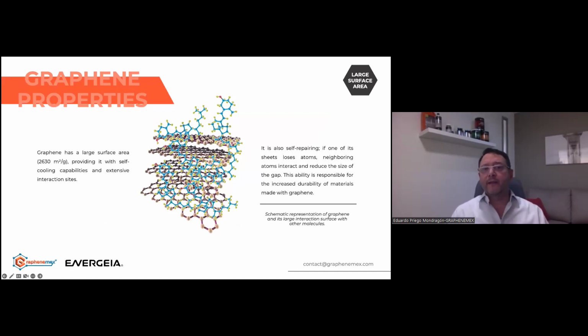Graphene has earned the moniker all-in-one material, and that's because of its multi-properties. Graphene has a large surface area. 1 gram can cover 2,630 square meters. That's equal to a football field, depending on its characteristics. This allows the material to have self-cooling capabilities and extensive interaction sites. It is also self-repairing. If one of its sheets loses atoms, neighboring atoms interact and reduce the size of the gap. This ability is responsible for the increased duration or durability of materials made with graphene.